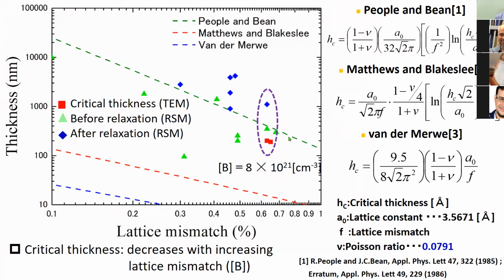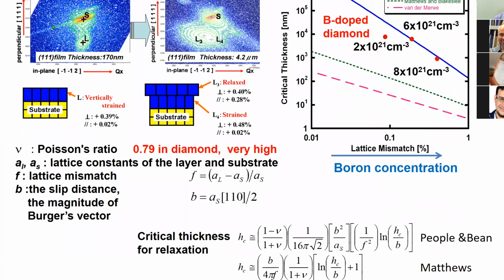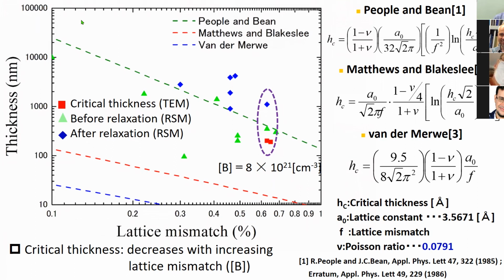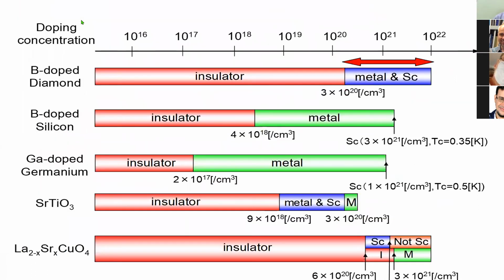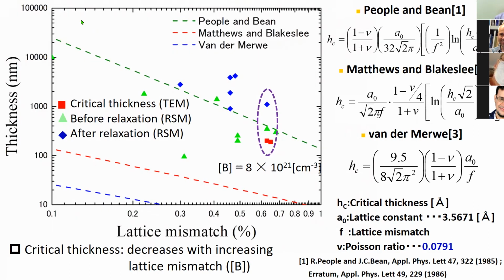So anyway, what we changed is the boron concentration, high. Then we get from the X-ray measurement nearly 0.7%. That's what we observed from this kind of measurement in reciprocal mapping.